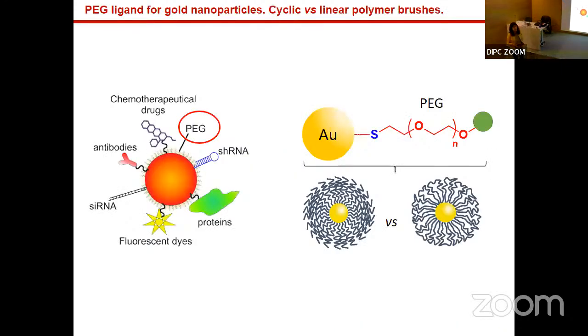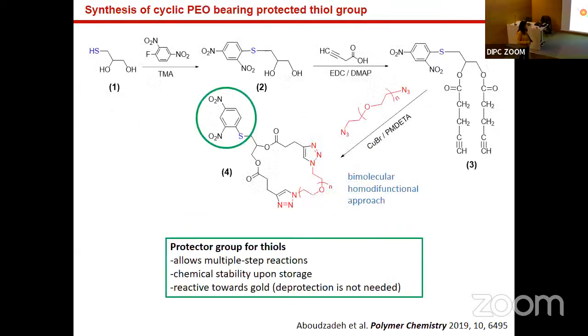Polyethylene glycol is very much used in the stabilization of colloidal metal nanoparticles. And in this project, we thought, what happens if we use cyclic polyethylene glycol instead of linear polymers? Is something going to change? Yes, things change, as I will explain. First of all, we developed a strategy to synthesize the cyclic polymer that contains a thiol group, because the thiol group is important to attach to gold.